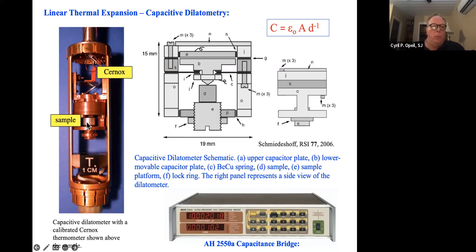But essentially, we see a sample right here. That's actually an aluminum slug, which is a standard. Using the cutaway here, a sample, represented here as D, expands or contracts depending on whether it's warming or cooling, and you can push this against the lower capacitor plate. This is an upper capacitor plate, and this is the gap right in here. As this sample gets longer or shorter, the capacitor monitors the distance between the capacitor plates.